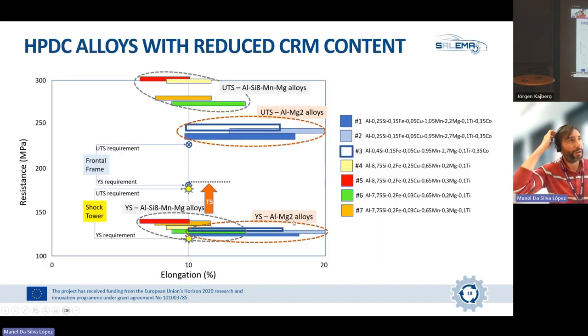For further development, we went into a high pressure die casting machine, also with a testing die, and produced parts for 7 different alloy variants, and we measured the mechanical properties achieved. With those alloys, we observed that most of them, as in the previous one, met the requirements in terms of yield strength and ultimate tensile strength of the shock tower. But we had more issues regarding the frontal frame. Also with a T5 heat treatment, we expected to solve this and cover the gap between the actual mechanical properties and the requirements.